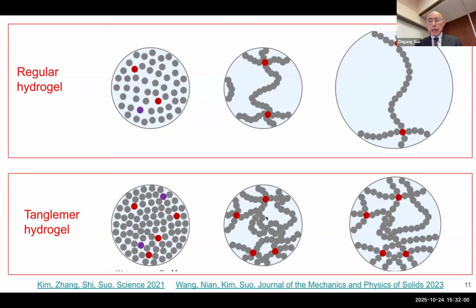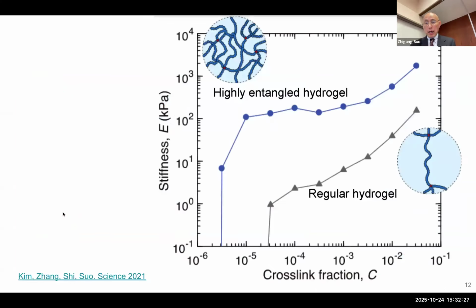Okay. And then he still needs to do the last step to make a stable hydrogel, by putting this thing, after crosslink, you swell it. Now, notice, after crosslink, when you swell it, the entanglement cannot be disentangled because you already crosslinked it. The entanglement is locked in. So that's how he prepared Tanglemer. So now some results.